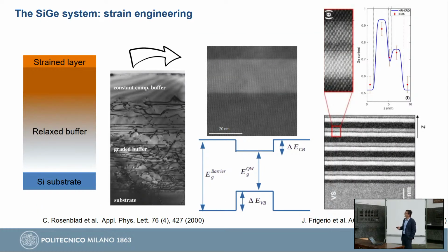So the typical structure of one of the samples we make in our lab is like this. We start from a silicon substrate most of the time. We can also grow on other substrates, but most of the time it is silicon. And then we grow a very thick layer, which is a relaxed buffer. Here you see a TEM image of a structure like this, where you have all these black lines, which are the crystal defects, dislocations, which are required to release the strain. And on top of this, we can put a strained layer.